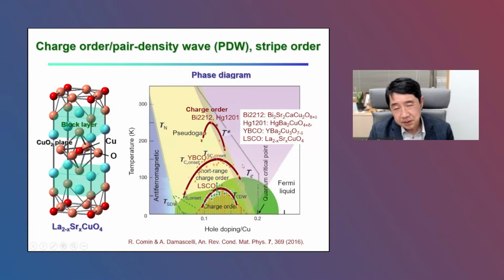Sorry, I put another pseudogap line because ARPES always indicates this kind of pseudogap, or the Nernst effect also. But some other transport properties show this T star line. And so the charge order state occurs in most cases within the pseudogap, but the ordering temperature depends on the material very significantly, so that charge order by itself cannot explain the pseudogap phenomena. You can say the pseudogap promotes charge ordering, but to different degrees depending on the material.